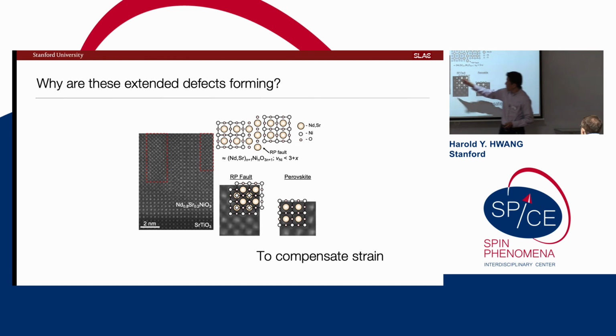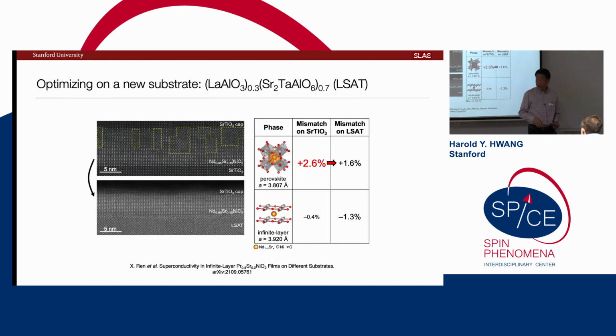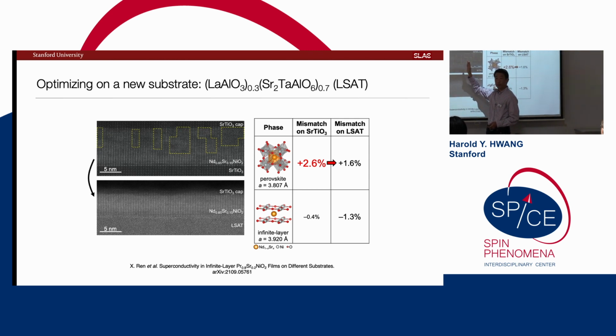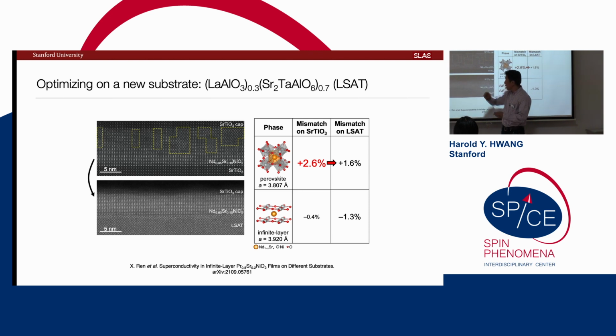So we grow this thin film, we have all of these extended defects, and what we're finding is that when we do this fairly low temperature deintercalation reaction, the cation lattice basically doesn't change. Okay? So whatever we grew is still frozen in there. We can't anneal it out, if you will.